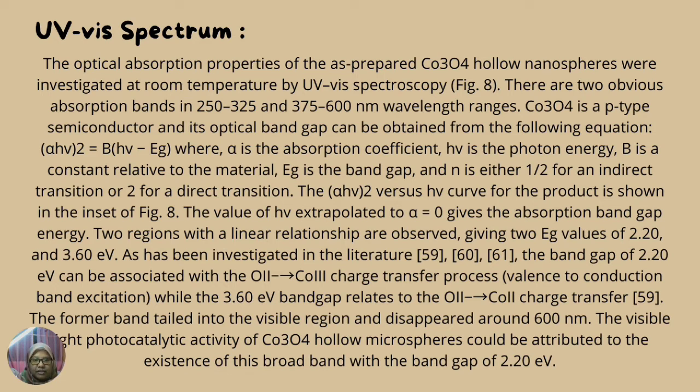The former band tails into the visible region and disappears around 600 nanometers. The visible light photocatalytic activity of Co3O4 hollow microspheres could be attributed to the existence of this broad band with the band gap of 2.2 eV.